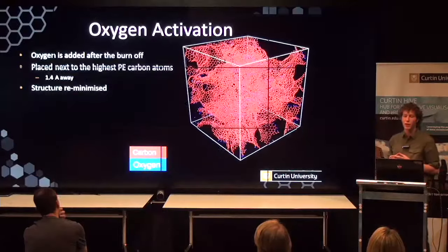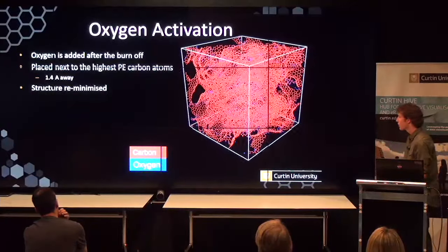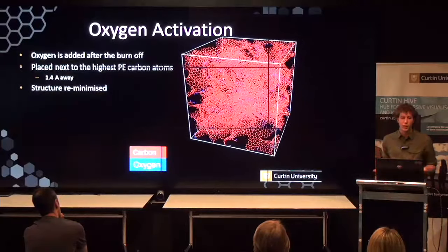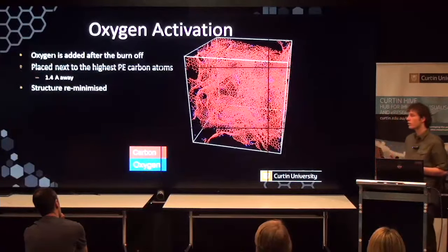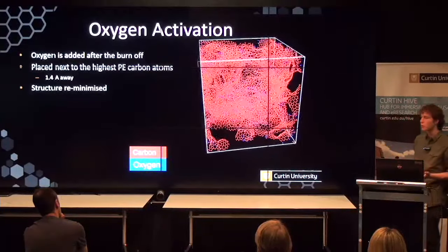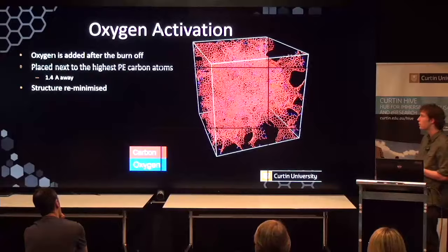In terms of how we added the oxygen, we once again chose the highest potential energy atoms as they're the most likely to be reactive, and then we placed oxygen atoms 1.4 angstroms away. And then we reminimized the structure once again using LAMMPS.